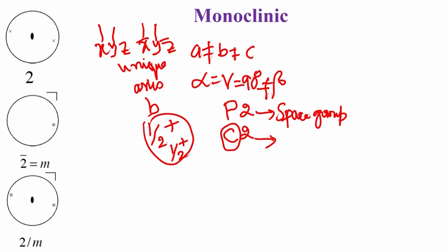Again, the definition of special positions might come up, or they may not come up, in a situation like this. For example, in a P2 system, if the object has a two-fold symmetry, then the object can sit on the two-fold symmetry, and as a consequence in that situation the number of equivalent points will turn out to be equal to 1. That will be a definition of a special position. In a C centered lattice as well, there will be special positions. The special positions can occur both due to the point group operation and also due to the centering operation, and therefore that needs to be examined more thoroughly, which we will do in the coming classes.